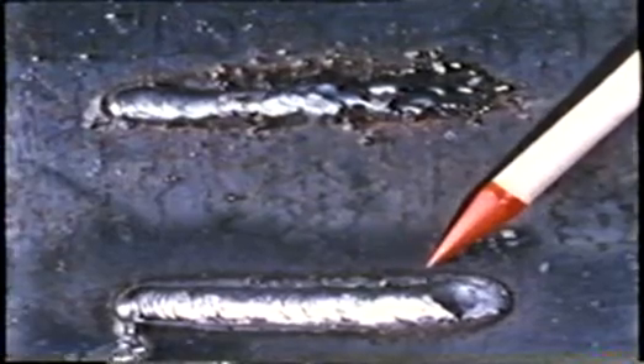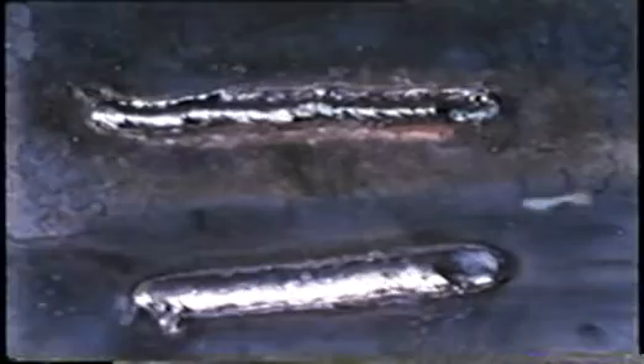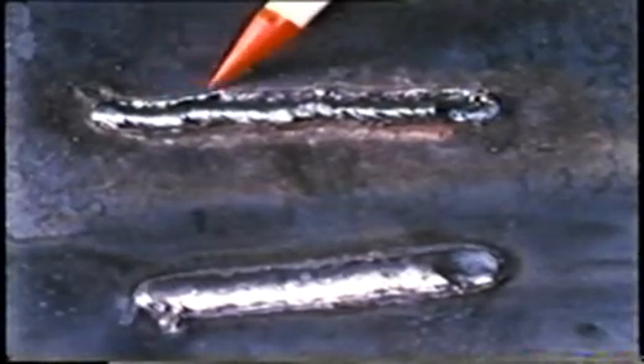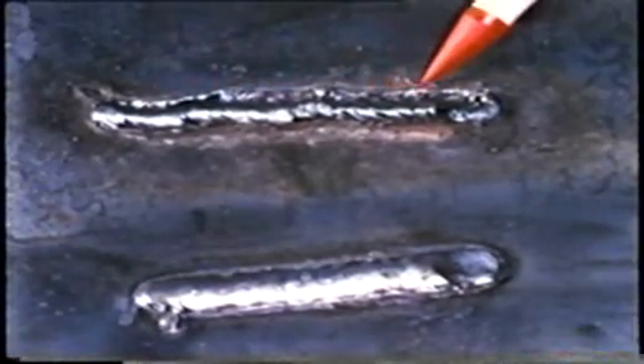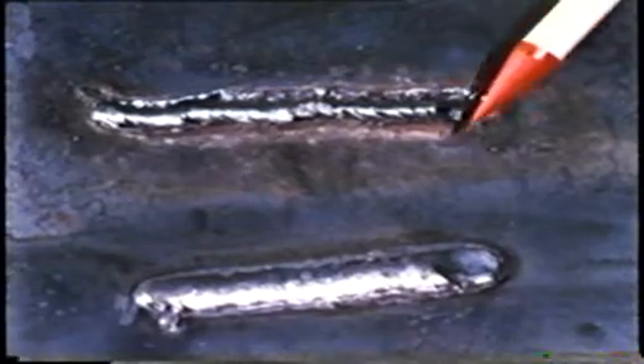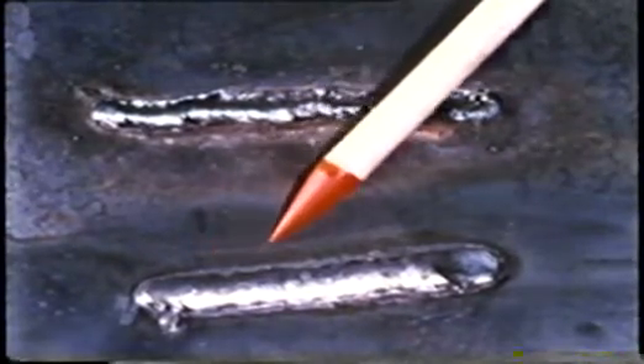An arc that is too short fails to generate enough heat to melt the base metal properly. The electrode is apt to stick frequently. The result is a high uneven bead with irregular ripples as compared to the correctly made weld bead.